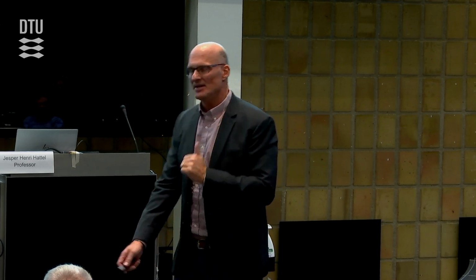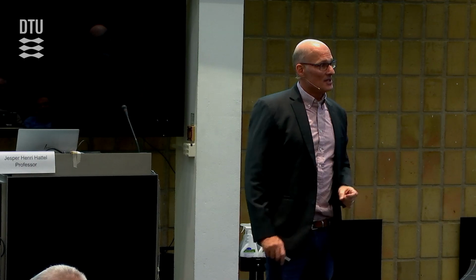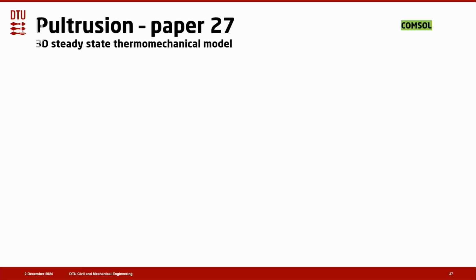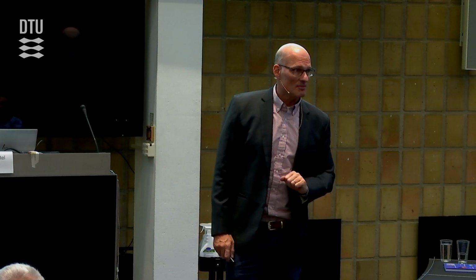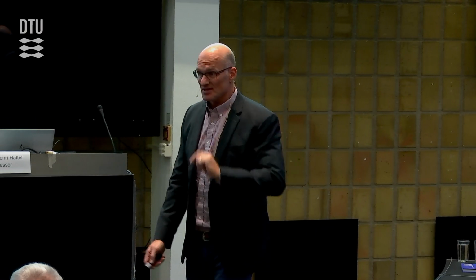Then finally, in pultrusion, we did a 3D steady-state thermomechanical model. Now, these other models were transient. That means time-dependent, and it means they take a lot of calculation time. It's not difficult to make a steady-state model for solving the temperatures, but it's more difficult to make a steady-state model for solving stresses and strains as well.